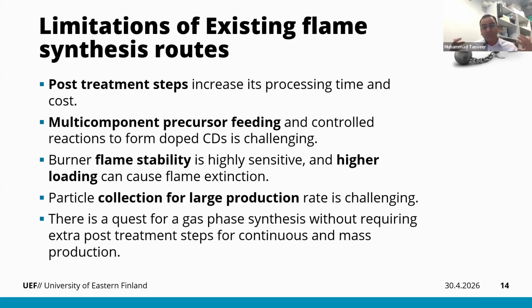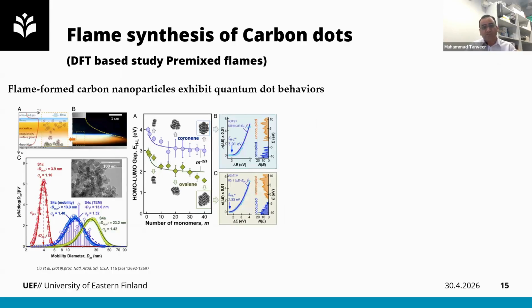So there is a big need for gas phase synthesis that can be used without any extra post-treatment steps, and that can provide continuous and mass production. In this respect, Liu has proposed a DFT model and suggested that through pre-mixed flame systems, we can produce some flame-formed carbon nanostructures which can exhibit carbon quantum behavior. So he has proposed that we need to actually control the combustion condition so that we can control the size of the particles, and also we can induce some organic compounds in the composition of the carbon dots, like the PAHs basically. If we can control them, then we can control its band gap, and there is also a need for a certain kind of graphitization, so that we can induce some structural defects also.